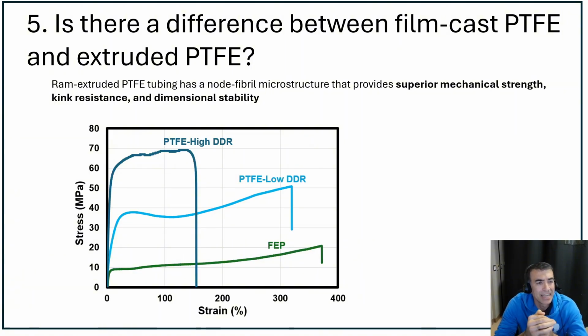FEP, on the other hand, is not that sensitive to orientation. It's not like PTFE, and the reason for that is the crystalline structure. The disruption that the copolymer brings to the molecules in crystallinity and crystallization would decrease the effect of orientation in making the crystalline shape. So the effect on PTFE is more significant. And when you do film casting, the effect of orientation is pretty low. So you are basically applying a very low DDR. So it's comparable to a RAM extrusion of PTFE, but at lower DDR.